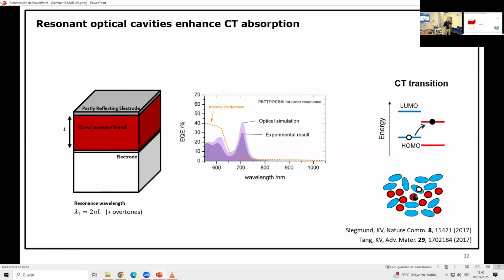Okay, it's more or less okay. It's a bit too simple. In wave optics, at the moment you can have a standing wave. So when half the wavelength fits perfectly in this thickness, optical thickness, refractive index times thickness, you have a standing optical wave. Then it gets absorbed very strongly. And with 2 metals, it gets, at least in theory, a factor 40 to 60 times stronger absorbed. So that's what we did.